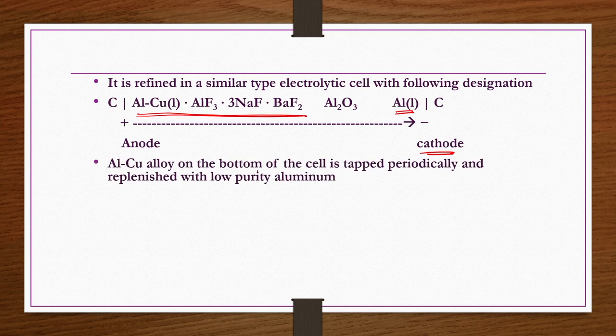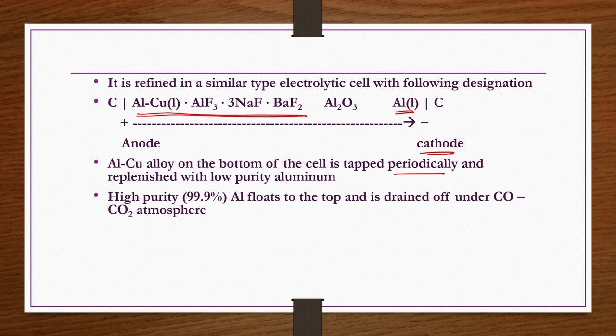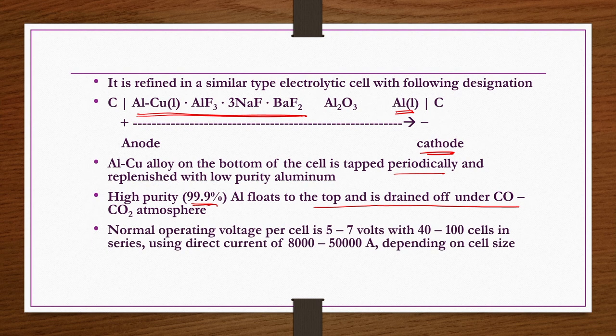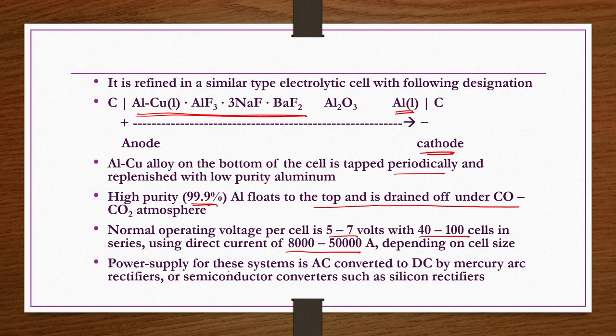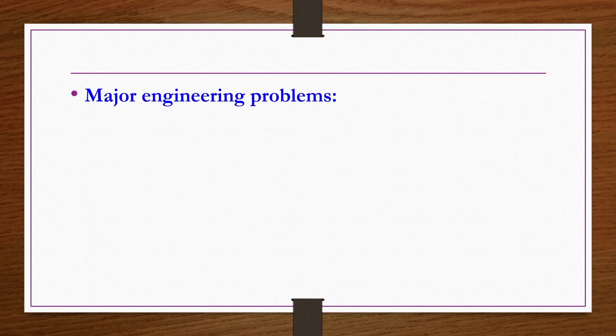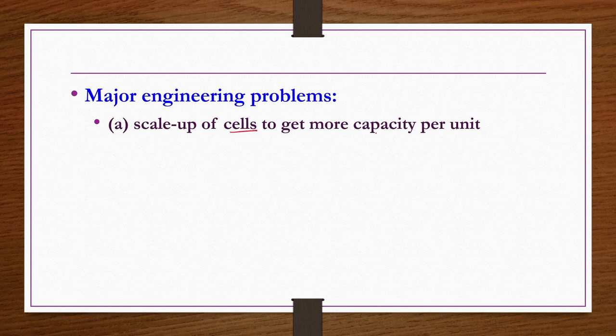So, aluminum copper alloy on the bottom of the cell is tapped periodically and replenished with low purity aluminum. High purity aluminum floats to the top, and this is drained off under CO, CO2 atmosphere, because in this reaction also CO, CO2 are forming. Normal operating voltage per cell is 5 to 7 volts with 40 to 100 cells in series, using direct current of 8000 to 50,000 amperes depending on cell size. Power supply for this system is AC converted to DC by mercury arc rectifiers or semiconductor converters such as silicon rectifiers.